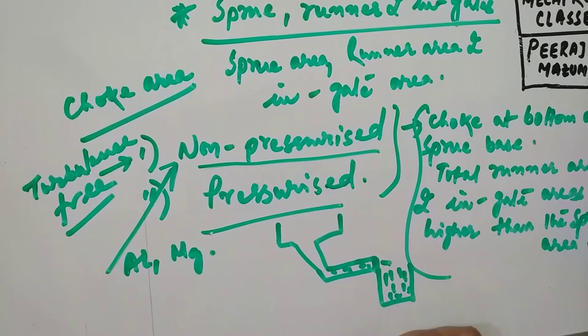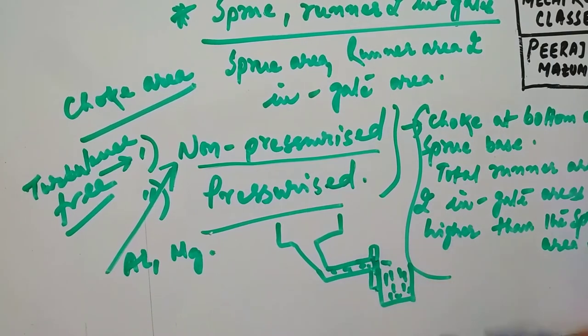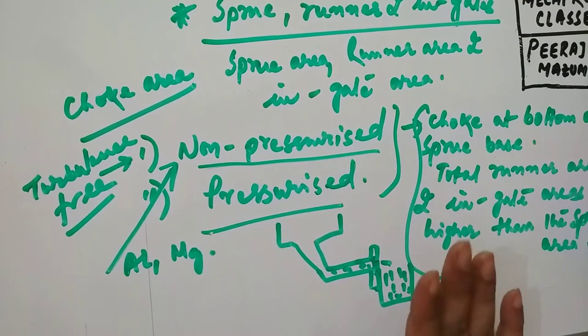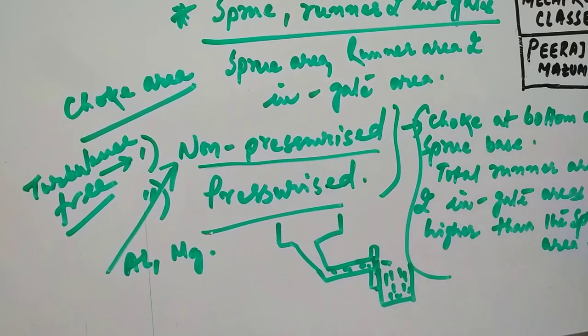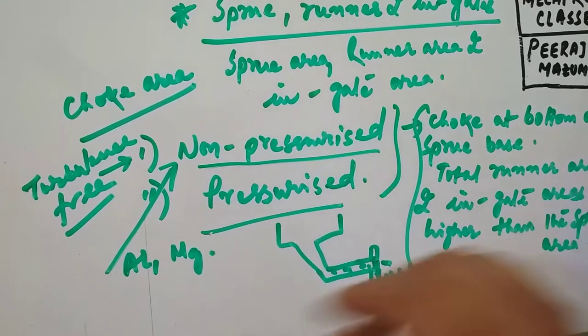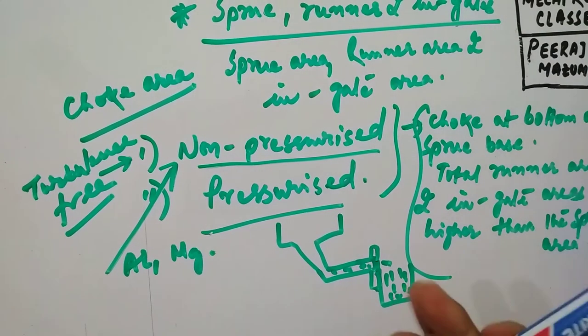You must keep in mind that when the metal enters the mold cavity through multiple ingates, say we are having different ingates, in that case of multiple ingates, the cross section area of the runner should accordingly be reduced at each runner breakup to allow equal distribution of metal through all the ingates. And the gating ratio is very important — you must keep in mind.